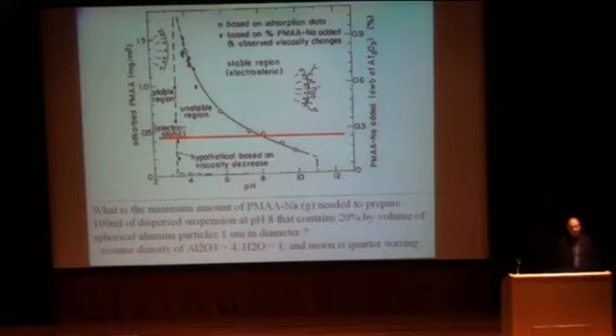I was told that I had to do this. So, Dr. Carden says that all the students should take a picture of this slide right now, so get your iPhones out. And if you can answer this question, you'll get some extra credit. So, you've got to figure out how much dispersant you would need at a pH of 8 to disperse a 20 volume percent alumina suspension for particles that are 1 micron in size.